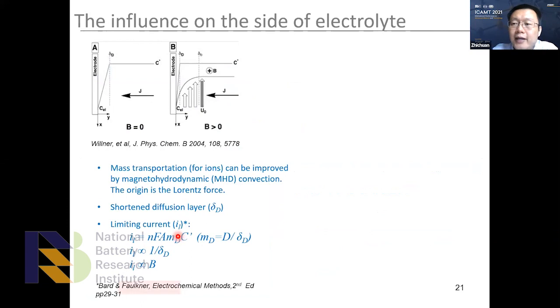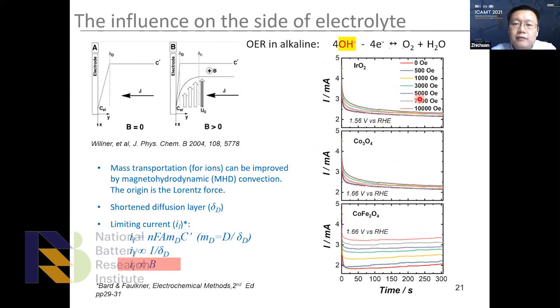And this is a known effect, right? And then we look back to our reaction. If we assume the reaction over here is hydroxide getting oxidized to oxygen, then based on the diffusion limiting current equation, we can derive that the limiting current can be correlated with the field strength. So if we apply the field, definitely we will see an increment of the limiting current. However, I should remind us, it looks like the increment is due to the promotion of mass transportation.